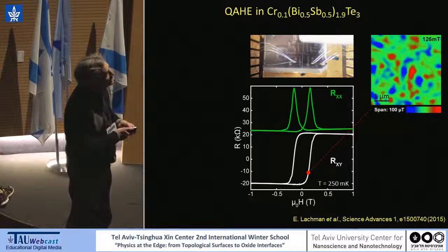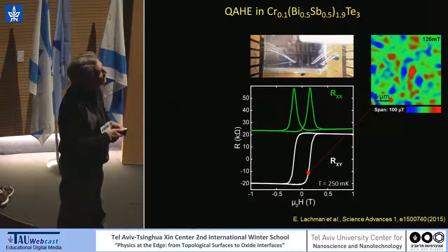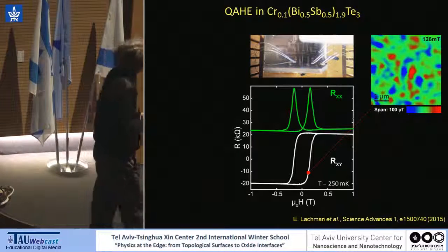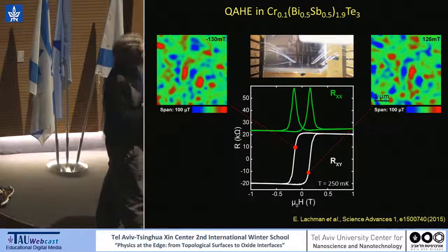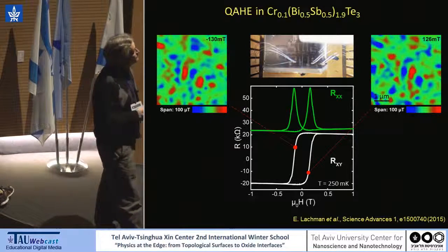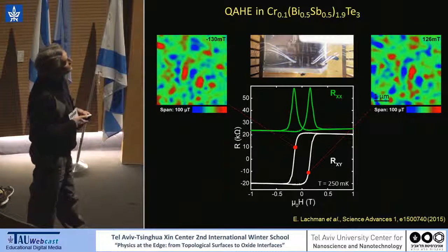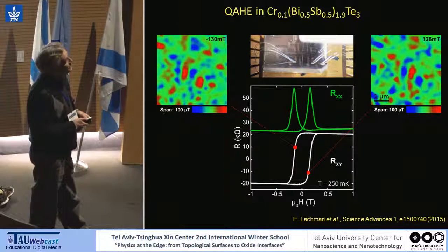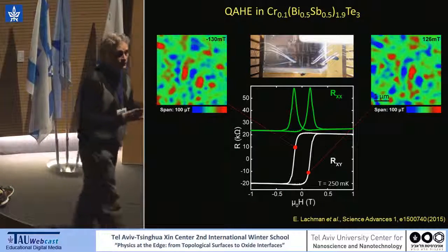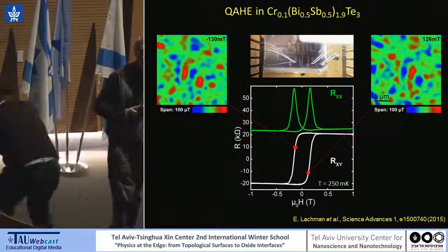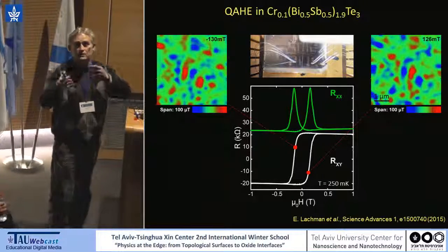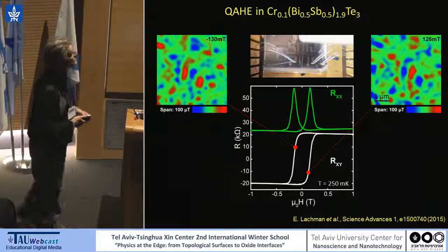Usually we would expect larger domains, but these are quite small domains. But this is what you naively expect from a ferromagnet near the coercive field. Now if we look at the diagonal point here, just coming back, you see a very similar picture. And if you look closely, you see that it's essentially identical, just with the colors inverted. So for example, here you have blue, red, blue. Here you see red, blue, red. This is a little puzzling because if it were a ferromagnetic film with domain structures, as you sweep the magnetic field, you wouldn't have to go through exactly the same sequence.